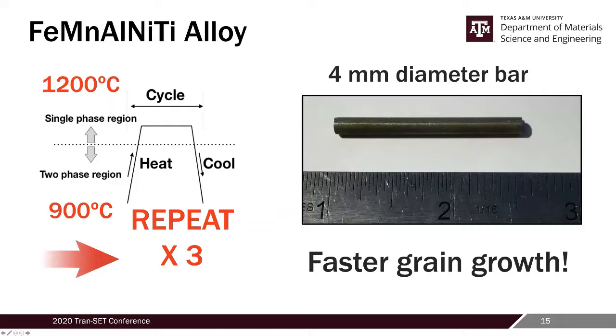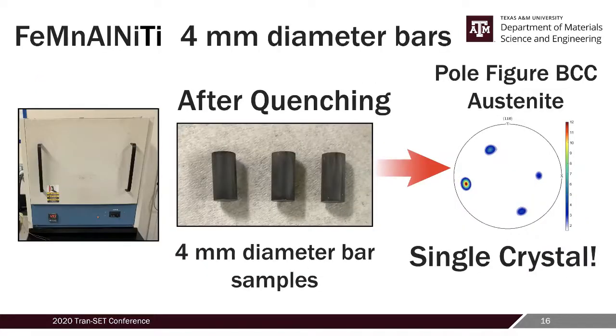And we also developed another alloy. We added some titanium into iron manganese and nickel. In this material, you can get much faster grain growth rates if you apply these heat treatment procedures. In this case, in iron manganese nickel titanium, we changed our heat treatment parameters to 900 C to 1200 C, so we cycle our material between these 2 temperatures. When you do that 3 times, you can get a single crystal in 4 millimeter diameter bars. Here you can see the samples that we heat treated. When we measure using XRD or EBSD, two different techniques, we saw that this material is a single crystal.